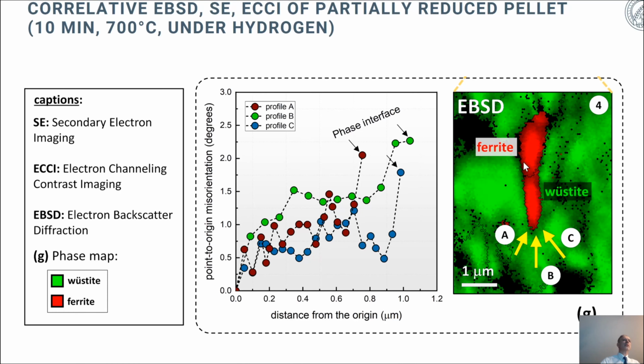Let us zoom in a little bit on one of these areas by using EBSD, which stands for electron backscattering diffraction, and we investigate again the interface between the red plotted ferrite and the green plotted wüstite. We take these three arrows of different length and plot them here, and reveal the point-to-origin misorientation coming from the outbound wüstite towards the ferrite interface. Then you can see the substantial buildup of orientation gradients before these interfaces due to the high stresses that are building up. And of course, these gradients are translated to corresponding GNDs, where GND stands for geometrically necessary dislocations, and again these defects can play a role for the local kinetics.